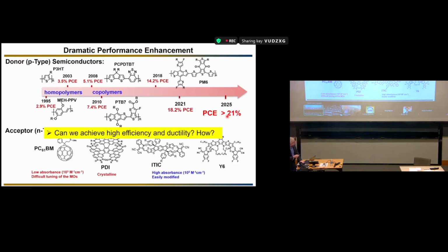What is the problem is that blends, if you take any of these acceptors, any of these donor polymers, no matter if the donor polymer is ductile or not, as soon as you take an acceptor and you put it into the donor, you embrittle the blend dramatically. So this becomes a very brittle blend. Also, if you start from a polymer donor which is quite, for example, stretchable. So can we try to find a new way to make some of these cells ductile?